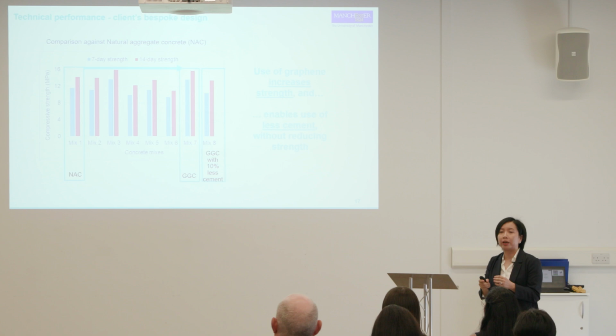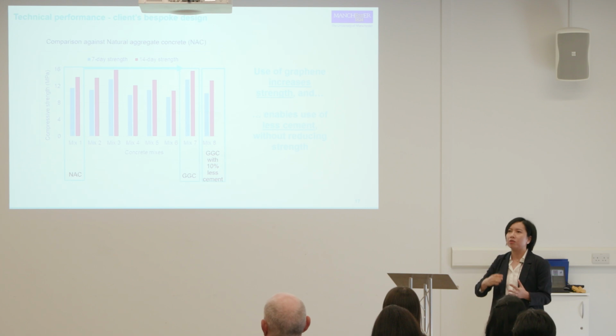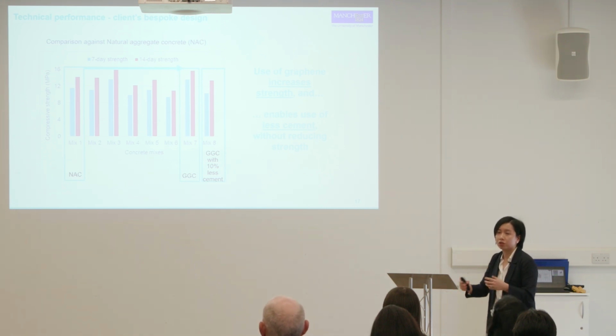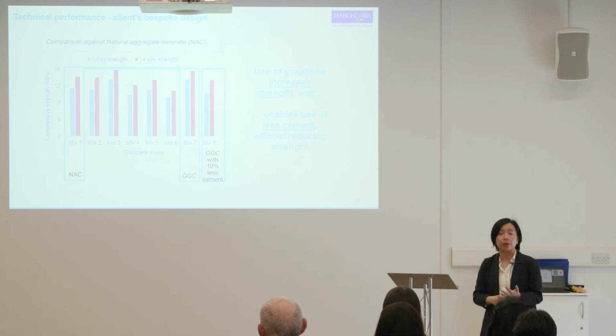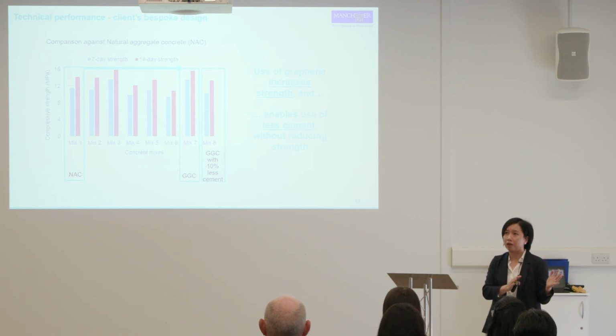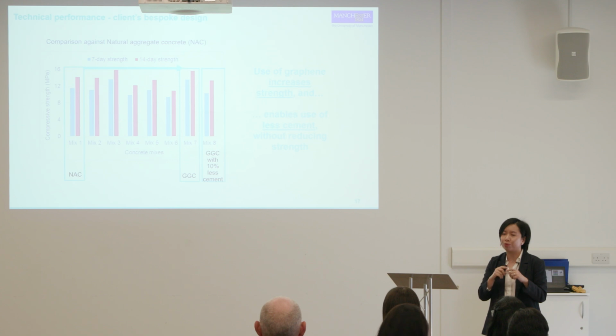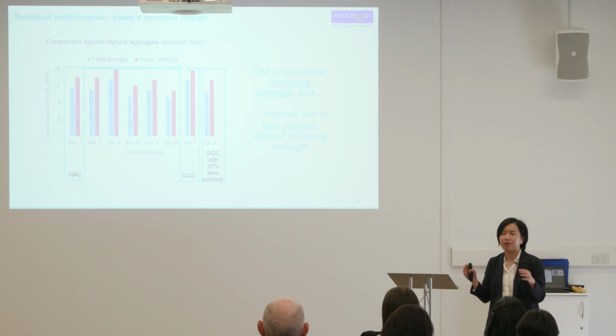And then in practical application, as I said earlier, we try to minimize the disturbance to the existing procedure. So when we do the practical application with the industry partner, we try to use the raw materials and then mixing formula provided by them. What we need to do is just do a little bit of validation at the lab before we do the large scale casting. So in terms of the recycled aggregates, we are basically open to all sources of recycled aggregates, because at the laboratory level, we chose the poorest quality of recycled aggregates to prove the concept, so that now we don't really have much constraint on the selection of recycled aggregates.